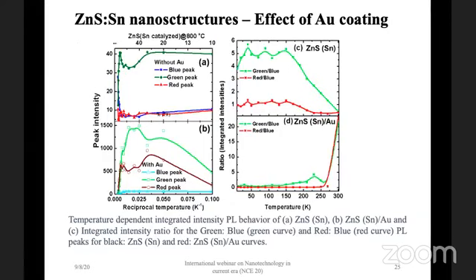We again did the analysis by plotting the Arrhenius plots, looking at the abnormal behavior, looking at the range where this amplification is happening and where this quenching is happening. We are in the process of making an explanation for these. This is what we have reached so far in these experiments.